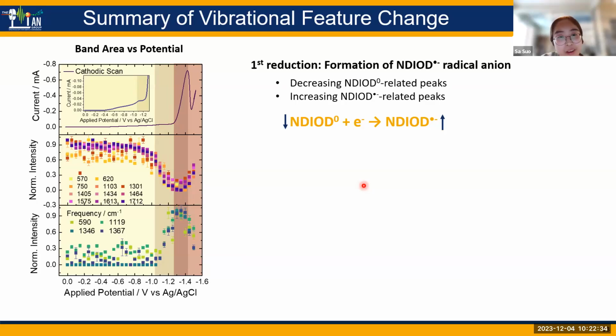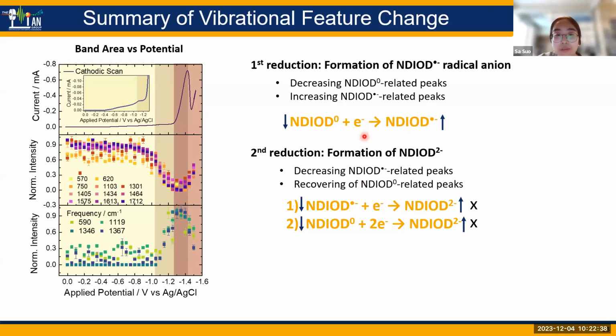But things get really complicated when it comes to the second reduction. Also predicted from previous experiments, they think the second reduction is due to the formation of the dianion. If we think of the two possibilities of the reduction, the first one could be the radical ion getting one electron reduction and forming the dianion, or the neutral N2200 goes through a two electron reduction to form the dianion. But what we see from Raman is that the neutral N2200 Raman intensity actually increases or recovers. Meanwhile, the polaron related peak or the polaron is consumed. Neither of these can explain the recovery of neutral N2200 peaks.